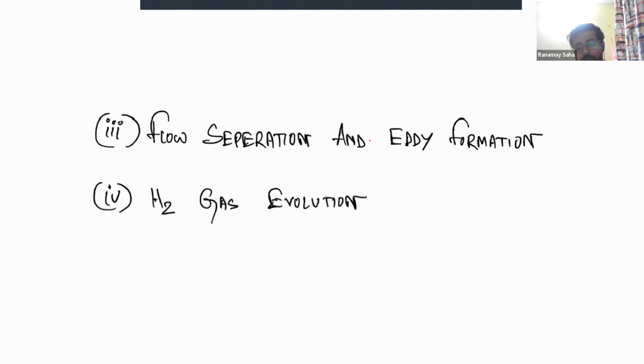and this can lead to reduction in conductivity of the electrolyte. Okay, so these may actually lead to an increase in the downstream. The concentration of hydrogen bubbles may increase in the downstream, and this can in turn lead to deterioration of your electrode surface. Okay? So these are the four major reasons for which the tool deterioration takes place. Sorry, work deterioration takes place, and that is followed by your actual tool design, which needs to be taken up. So that's how I think we can conclude today's session. And if you have any doubts, you can just shoot now.